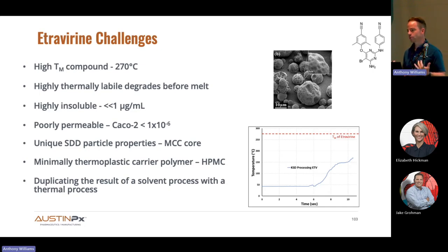It's a BCS4 molecule, so that presented some challenges as well in terms of trying to match Intelence from a bioequivalence perspective. It's not just a matter of dissolution rates and solubility. It's about presenting it at the right place in the GI tract. And we're working with this high melt compound, with a minimally thermoplastic polymer in HPMC. So it's not helping us out in terms of viscosity and polymer dissolution. And beyond all this, we are duplicating an amorphous solid dispersion made by a solvent process with a thermal process. It's very dissimilar technologies trying to establish a bioequivalent product. It's a big challenge, but we were able to do it.